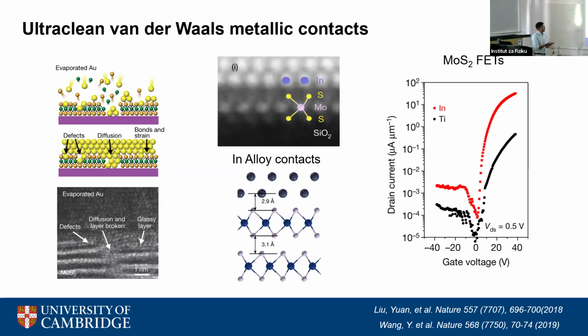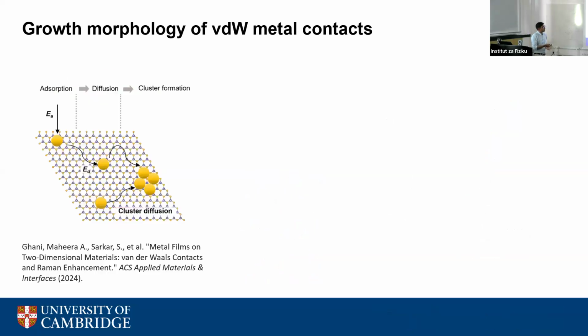When I joined the group, I was co-supervising with Manisha, a PhD student, and we started a small project where we really wanted to know how these van der Waals contacts grow on the surface of 2D materials. This is a very general schematic of how metal contacts grow. When you deposit a metal, the atoms adsorb and move around the surface of the 2D material, and they need to nucleate at a certain point. Now, where do they nucleate?